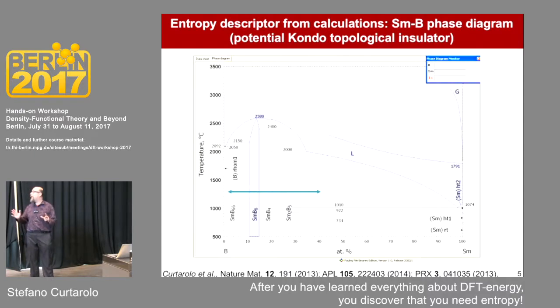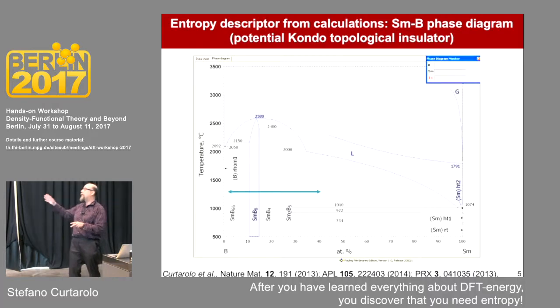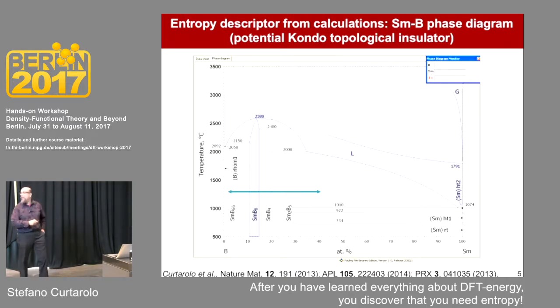And then the vapors recombine, okay? Since you can control the power of the laser and you can measure the partial pressure of the gases, you pretty much know the concentration of the gas, whether it is boron rich or samarium rich, you understand? And then slowly this gas recombines and grows on a substrate a phase that is compatible with the concentration of the gas. Okay, so Ichiro comes to me and says, hey Stefano, whichever the concentration of the gas is, if I go from the left arrow to the right arrow, I always get samarium boron 6. This is a paradox, because if I were at the concentration of samarium boron 4, I should form samarium boron 4.